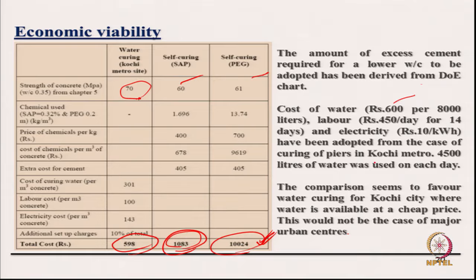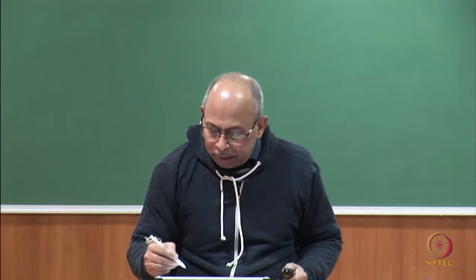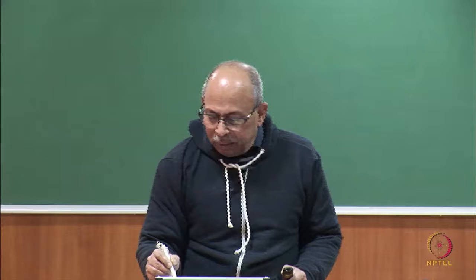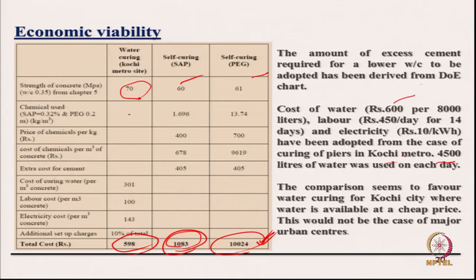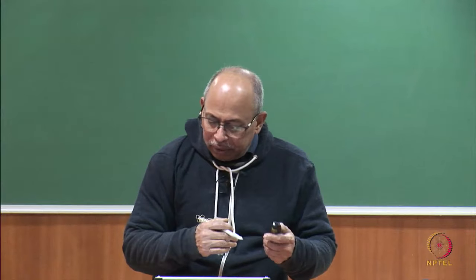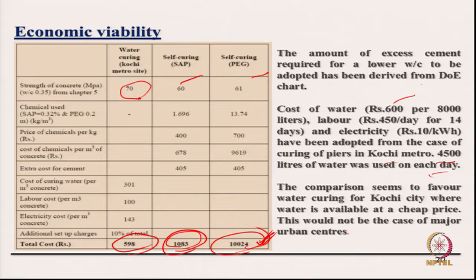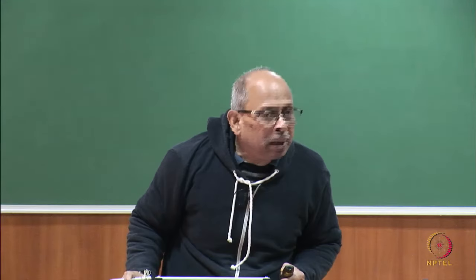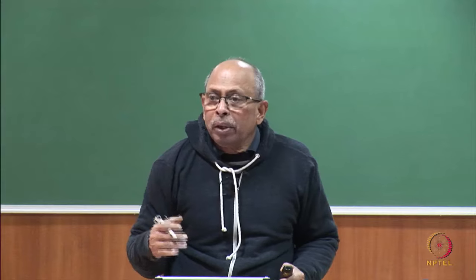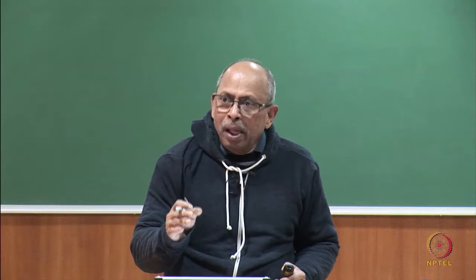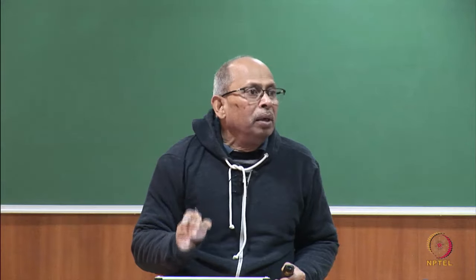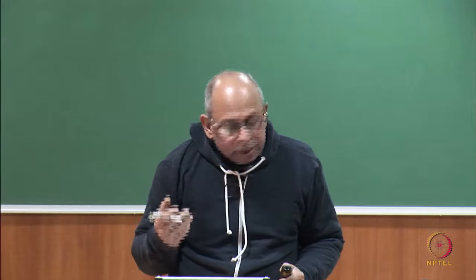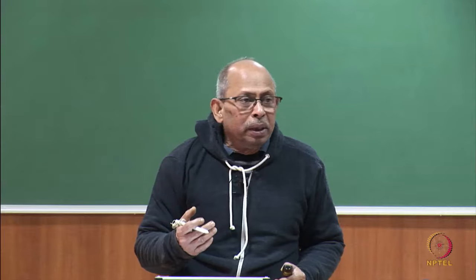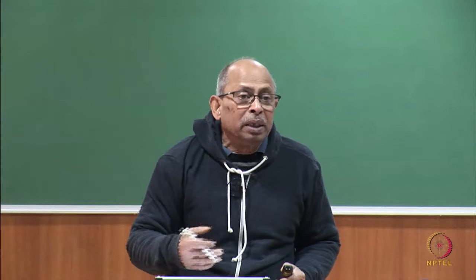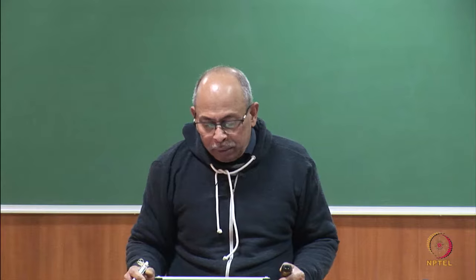So, you have to see what is more important here if you are using curing admixtures. In the particular case that we looked into for Kochi Metro, because I want to get the same strength, at lower water cement ratio strength gets reduced. So, I might use more cement and the cost increases with this kind of material for the same strength. You have to see the economics part of it, but these options remain, and possibly more research would show that one can use these admixtures economically. They have their advantages. Where water is absolutely scarce, one might try to use them. Where water scarcity is not so much, the problem is that the cost of cement will increase if you want to get a high strength system. In a low strength system you can still use this.